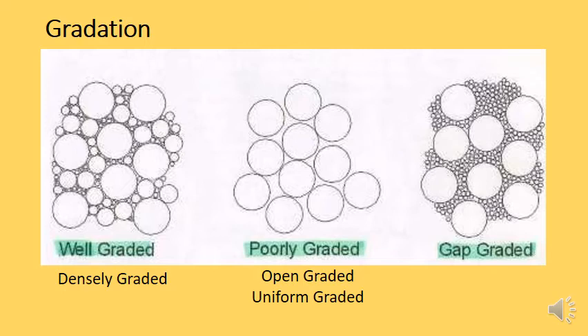Remember how we said porosity leads to poor durability, and if you're using it in concrete, that it will lead to lots of cracks in the concrete. We don't want that. That's why when we do eventually make concrete, either in this module or in concrete technology, we're going to be making gap graded aggregate for the concrete. We will be mixing 5 to 10 millimeter stone with sand.